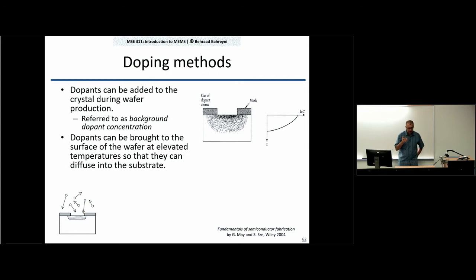So what we can do is that we can bring dopants close to the surface. Let's say in this case, what we do is that we cover portions of the wafer that we don't want to be doped with some masking material, it could be a dielectric, and bring dopants close to the surface and let them get into the material, let them slowly diffuse into the substrate, right?